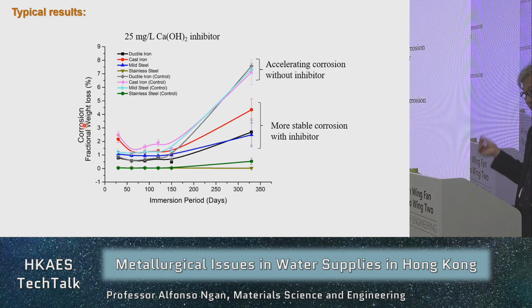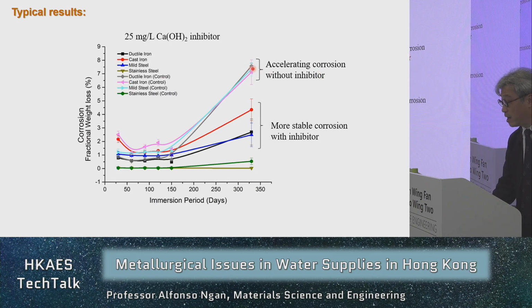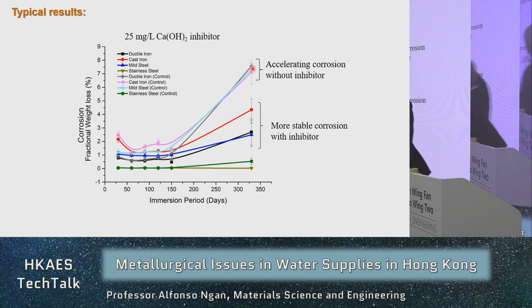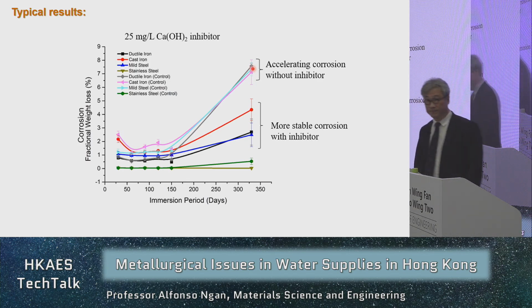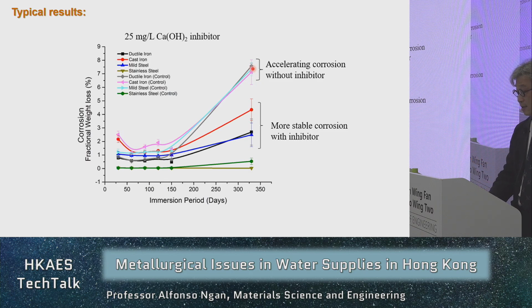So the difference in weight before and after, in terms of percentage, would be this scale, and the horizontal is the immersion period. So let's say if you look at ductile iron, if you have the calcium hydroxide inhibitor, the corrosion amount is only that much, but then without the inhibitor added, ductile iron would be this gray curve. It will be up there. Okay, so there is this much of difference for about a year. So in other words, adding this inhibitor would slow down the corrosion, would basically reduce the corrosion.